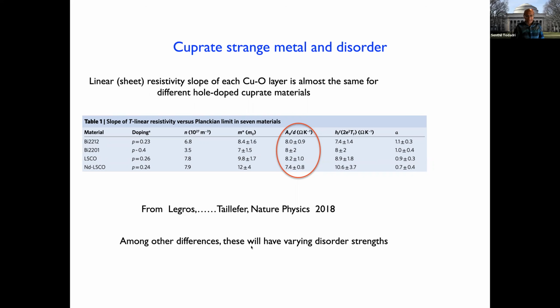So among other differences, they certainly will have varying disorder strengths, right? It's hard to imagine that these materials grown by different people and using different methods with different chemicals all have exactly the same kind of disorder, right? So the fact that they have the same slope strongly suggests that the slope doesn't care about the kind of disorder that you have or the extent of disorder that you have, okay? Consistent with the absence of a residual resistivity in the cleanest cuprates.